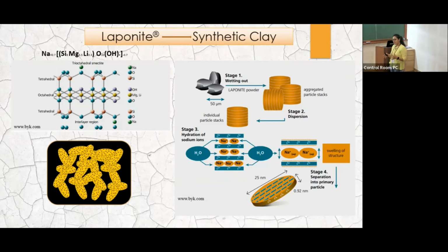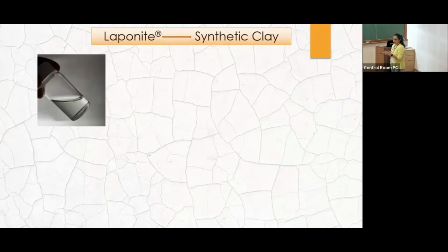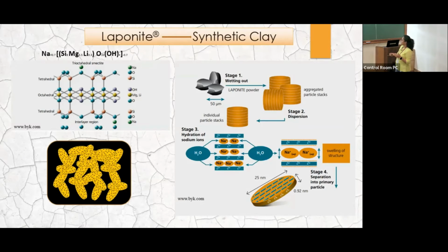These time-dependent electrostatic interactions between the charged particles give rise to the formation of microstructures, and that's how the suspension ages with time. It becomes elastic with time because of the formation of microstructures between these particles. Here in the bottom left is a schematic showing the house of cards arrangement of these disc-shaped particles. This aging property of the Laponite suspension is what we have used in our studies, to see how this aging mechanism can be incorporated to study interfacial instabilities.